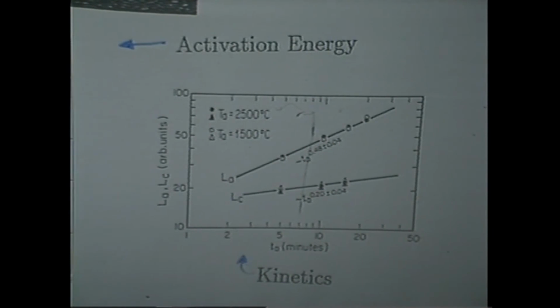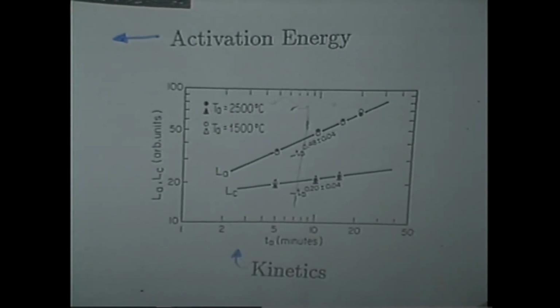And then you can do some kinetics to find out what the mechanism is, and you find out that it's a diffusion-controlled mechanism in plane. It goes like T to the 1/2 power, as you expect, but across the planes it's something different. That was also interesting. Well, some of the other things that we did, and I'm going to move through these things pretty quickly, is photoconductivity.